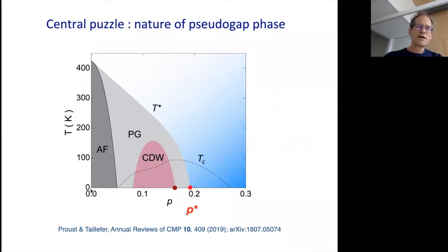And this is not a trivial insulator. This is a Mott insulator, made insulating by virtue of the strong repulsion between electrons. It's also an antiferromagnet. You can take that material all the way at high doping to what looks more or less like a conventional metal with the usual Fermi liquid signatures. So we have all this physics between Mott insulator and Fermi liquid that we can tune by adjusting the concentration of holes. And of course, in between, there's this fascinating, very robust and strong superconductivity.